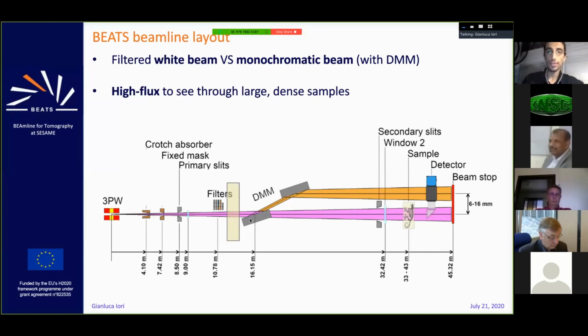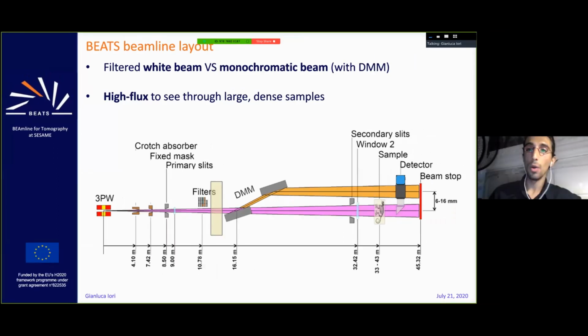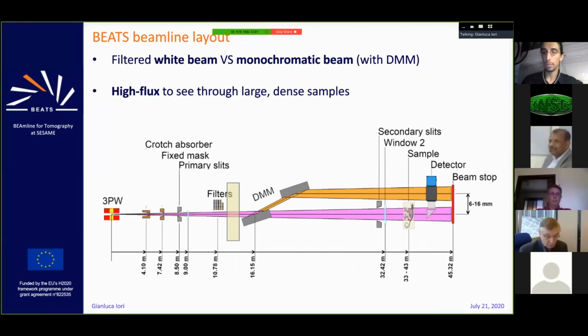After the filters, there is, as I said, a monochromator, which is a double multilayer monochromator. And you see already two of the modalities that we can actually target with BEATS. We have a pink beam, which means the monochromator is removed from the beam path, and we allow the whole X-ray flux to reach the experimental hatch. This is done when we need a high flux and we need fast experiments, so a lot of photons. When, on the other hand, we want to tune the energy for the experiment, we use the double multilayer monochromator, with a certain offset, as you see, which will vary between 6 and 16 millimeters, and bring the monochromatic beam in the experimental hatch.